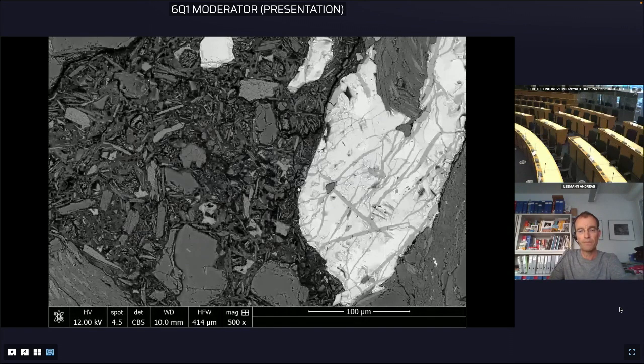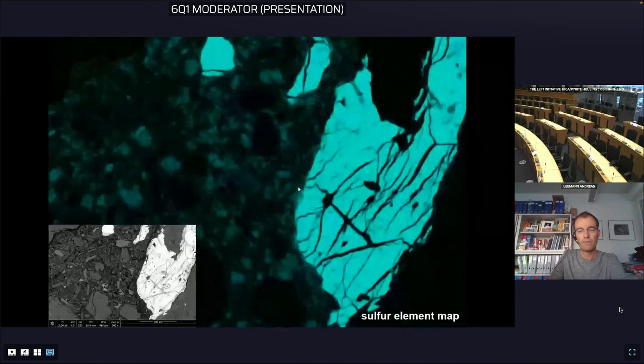Next, please. Okay, the brighter the blue, the more sulfur is here. So you see, of course, pyrrhotite stands out. However, you see these bluish pockets in the cement paste. And now you can perform more element maps and form a so-called phase map. Next, please.